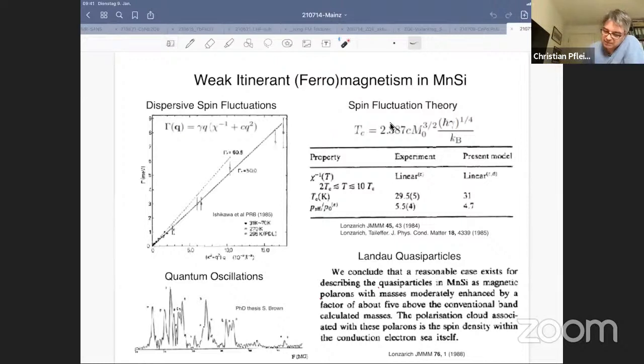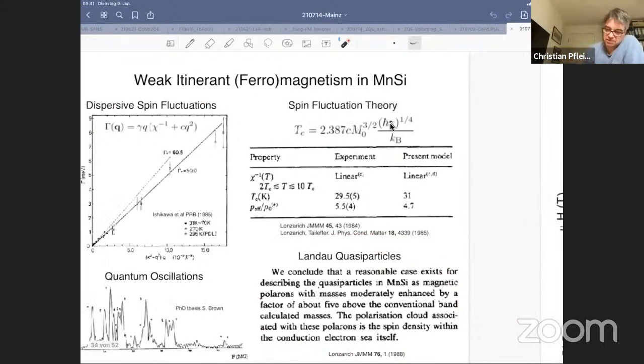So he was interested at the time in coming up with an explanation for the dressing clouds of quasiparticles, and he was able to connect the spin fluctuations with the dressing clouds of these quasiparticles. I will show you in a minute how this works, but basically the idea is that you have a full account of the enhancement of the Sommerfeld coefficient of the specific heat, on the one hand through the quasiparticle spectrum you see in the quantum oscillations, and on the other hand what you see in neutron scattering measuring these spin fluctuations.